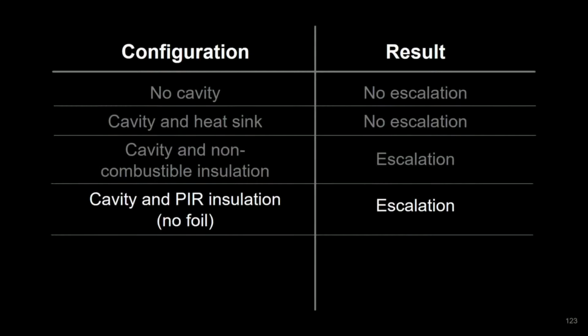I removed the foil facers from Celotex RS5000 in an attempt to maximize the possibility of an energy contribution from the PIR foam to the fire. And in this experiment, I also observed escalation. From analyzing the data, I concluded that this occurred slightly earlier than for the equivalent case with non-combustible mineral wool insulation. This may be because of an energy contribution to the system from the combustion of pyrolysis products coming from the insulation itself. The insulation did ignite rapidly and did spread flame over its surface in this configuration.